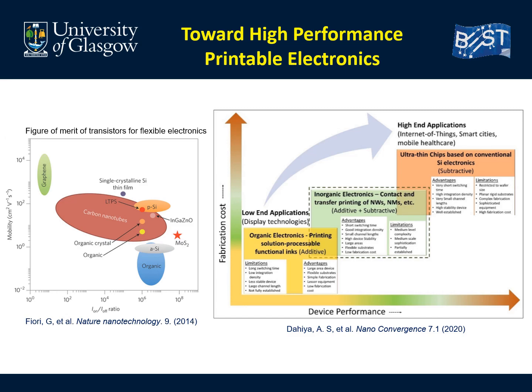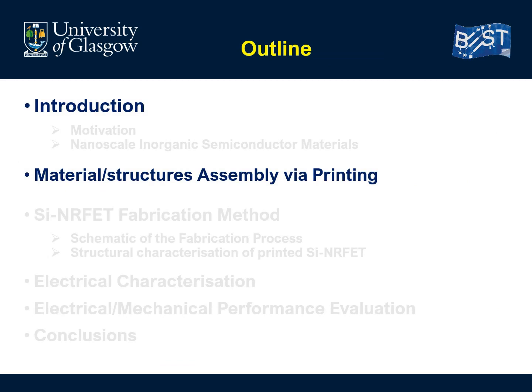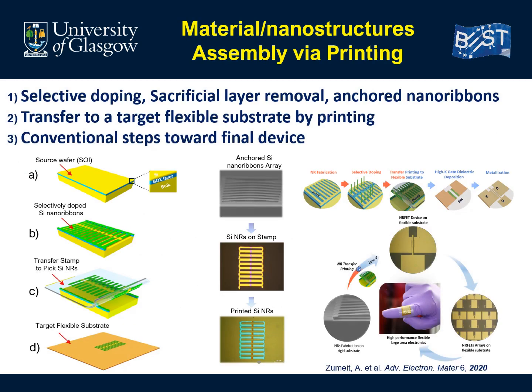So when it comes to integration and assembly of nanostructures on flexible substrates, the transfer printing technique can provide a solution, especially since it allows the nanostructures to be transferred from the source wafer to the receiver in a high yield manner and with good alignment. In general, this method can be done using a soft intermediate elastomer stamp. Printable single crystal silicon, such as nanoribbons, can be achieved using an SOI wafer, where the buried oxide layer serves as a sacrificial layer, as you can see here from the schematic.